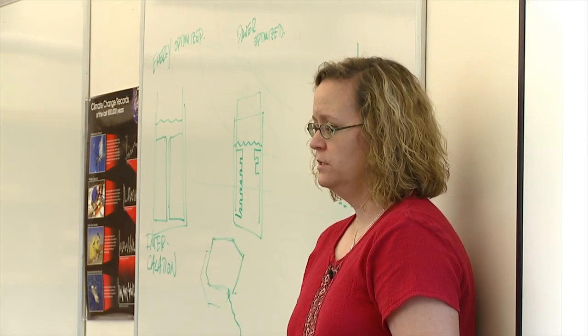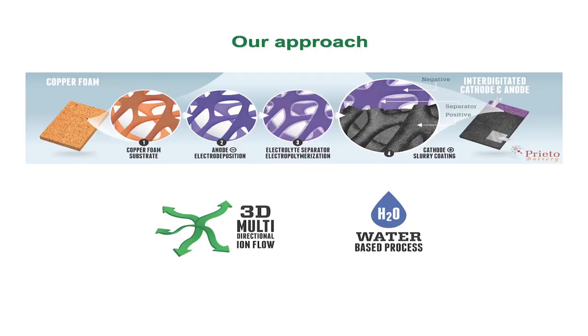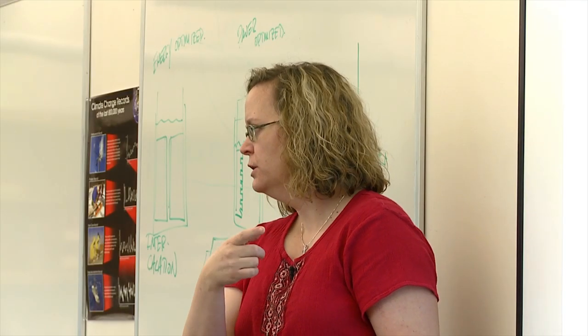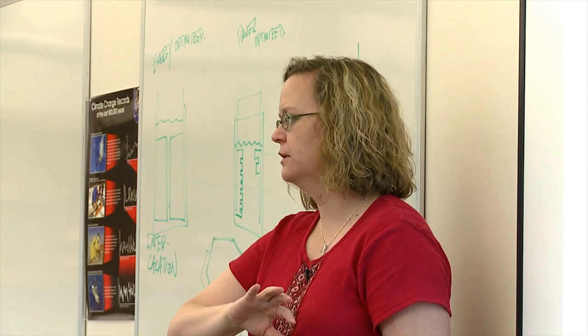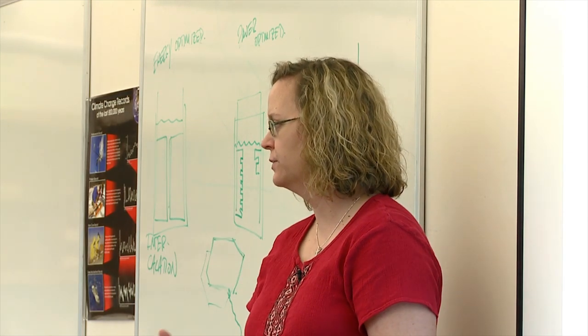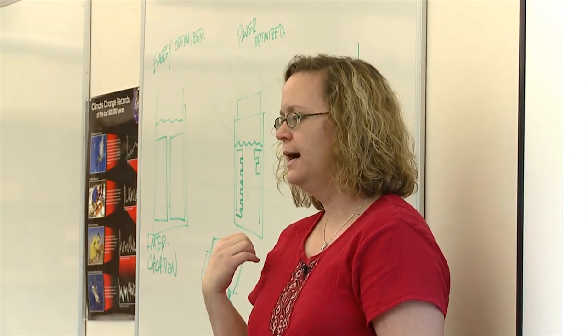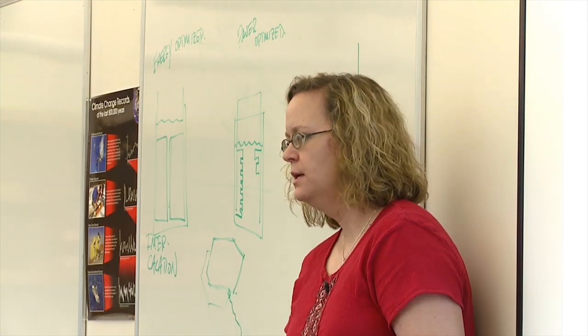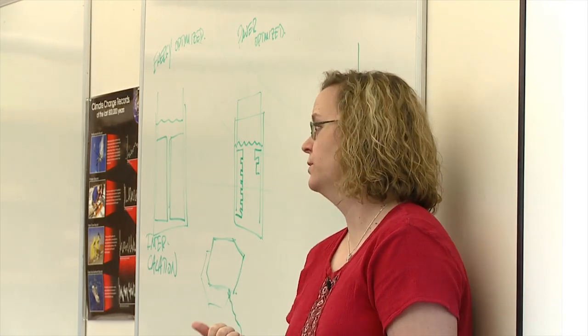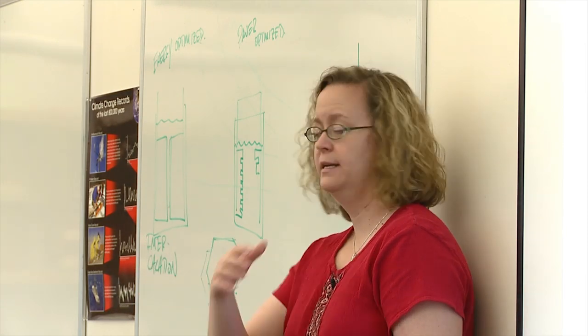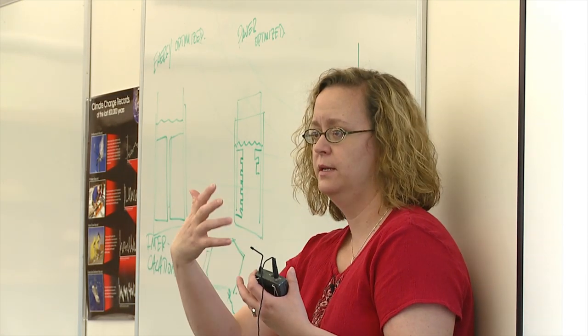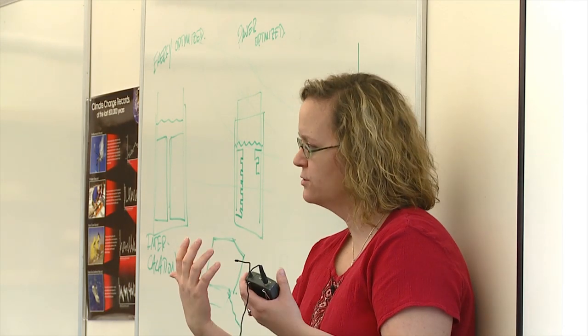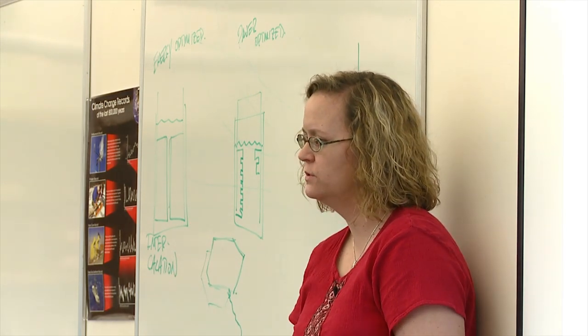So current batteries have a porous separator, it's called. It gets soaked in this liquid electrolyte and it mechanically keeps the anode and cathode separated. We can't really have that because of our architecture. So we had to come up with a way to basically conformally coat every nook and cranny with this polymer electrolyte. It has to be mechanically stable, but it has to be mechanically flexible because remember I told you the electrodes expand and contract, and now ours are interdigitated, so they have to expand and contract kind of in concert with each other, and the polymer has to be flexible enough to accommodate that.